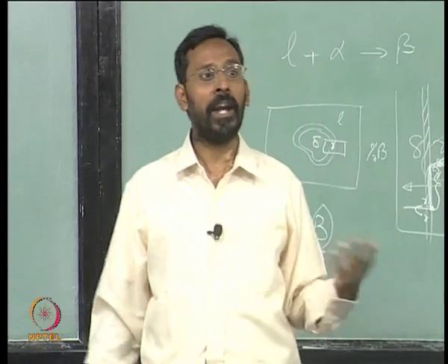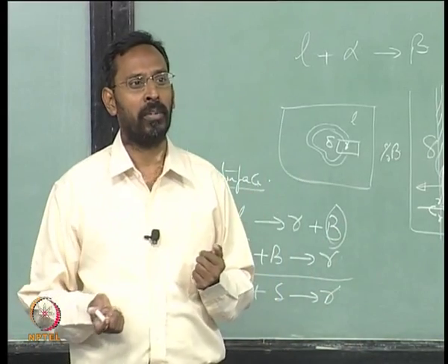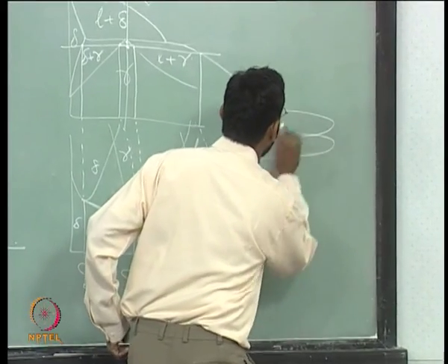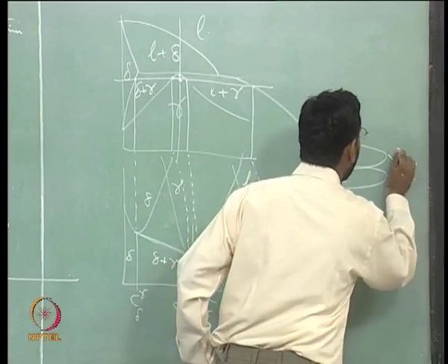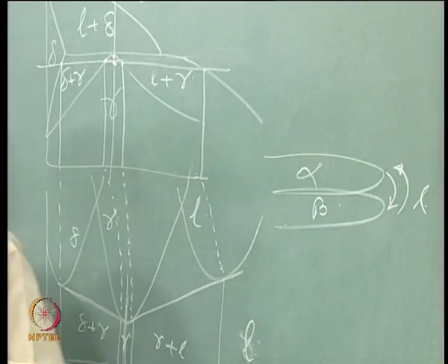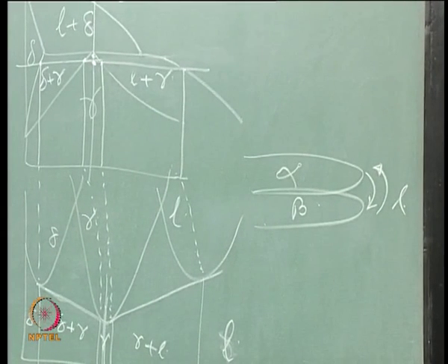Diffusion inside the liquid, as in the eutectic reaction, is very easy. Why? Because all the diffusion of atoms that is happening, if you remember the alpha plus beta, we said liquid, all the atomic movement is taking place inside the liquid, and they are moving faster. That is why the eutectic reaction is definitely much faster than a peritectic reaction.